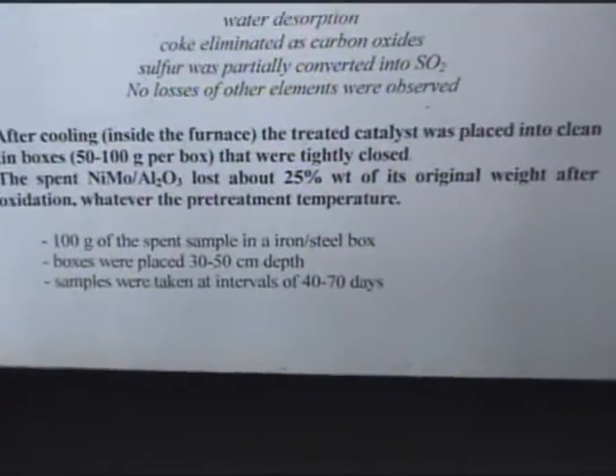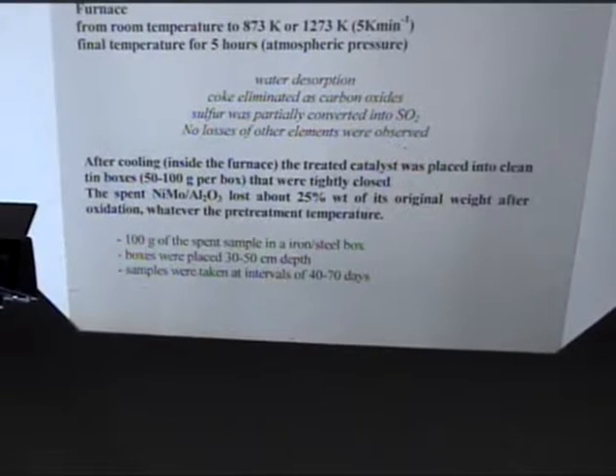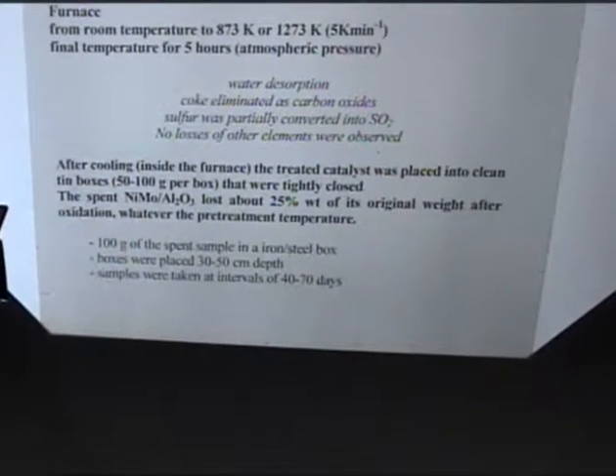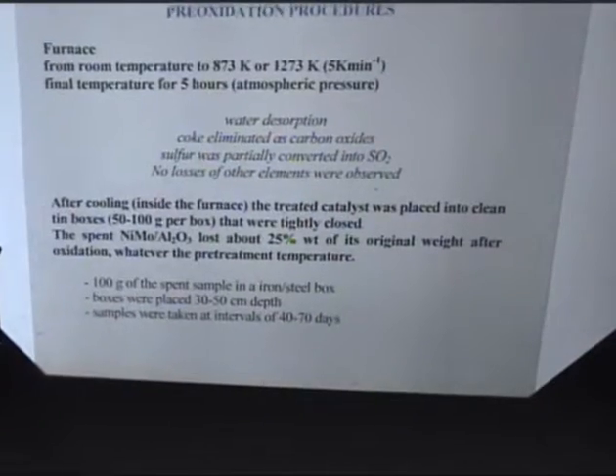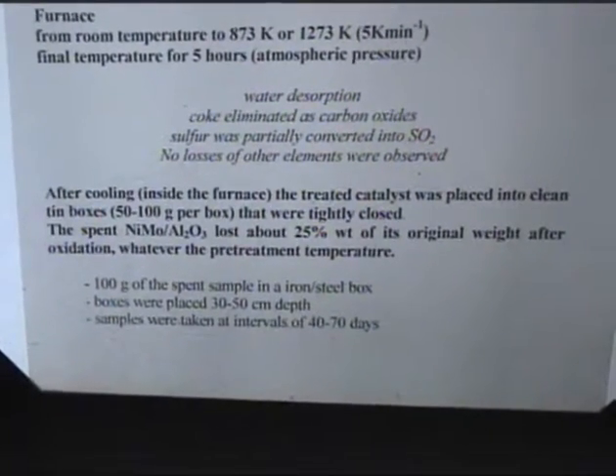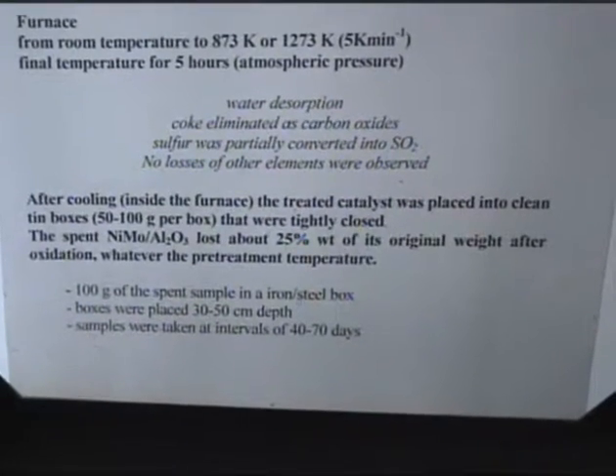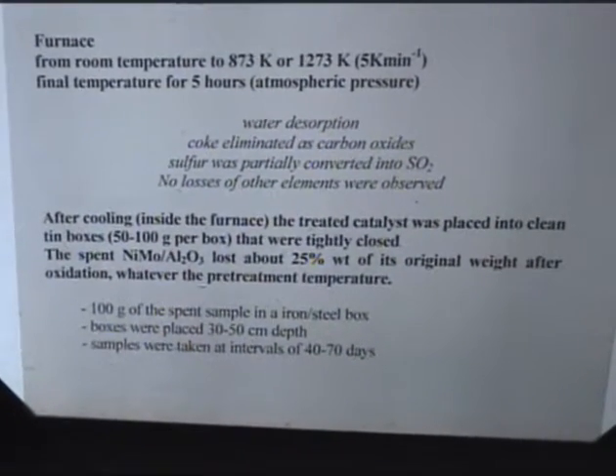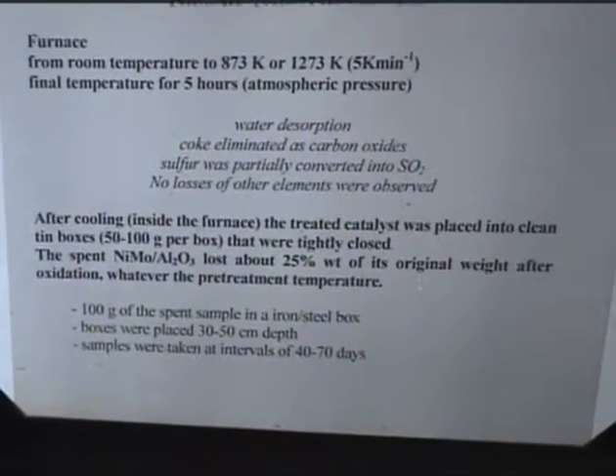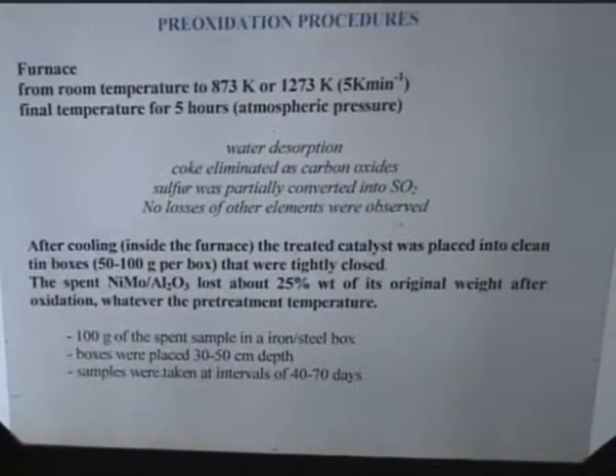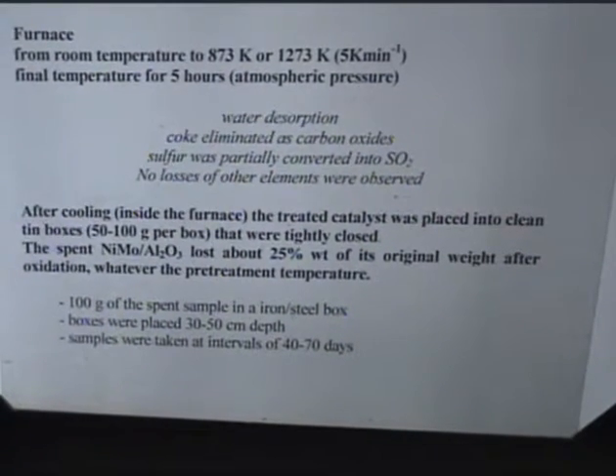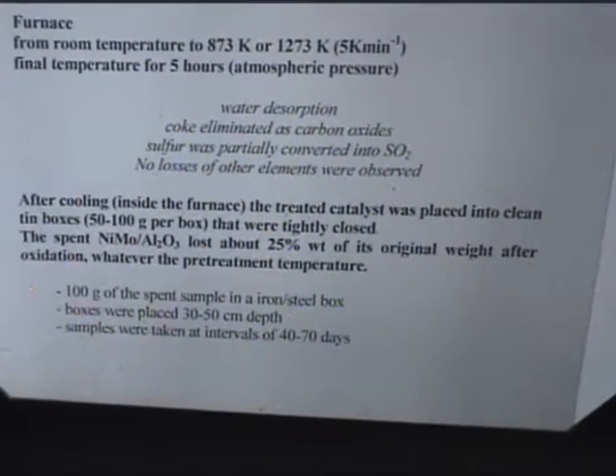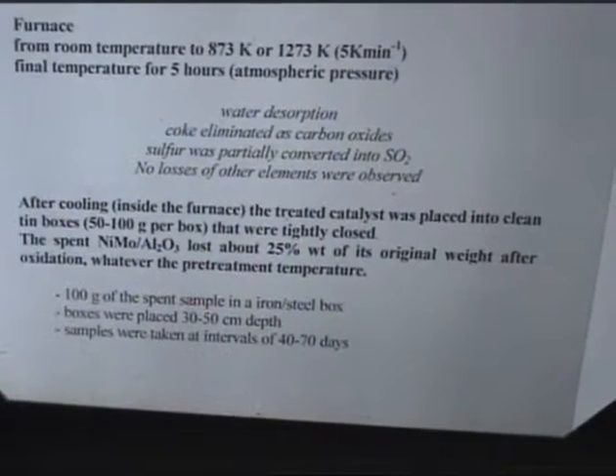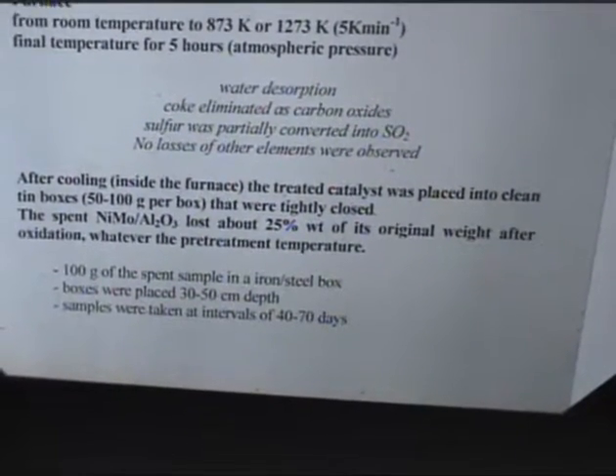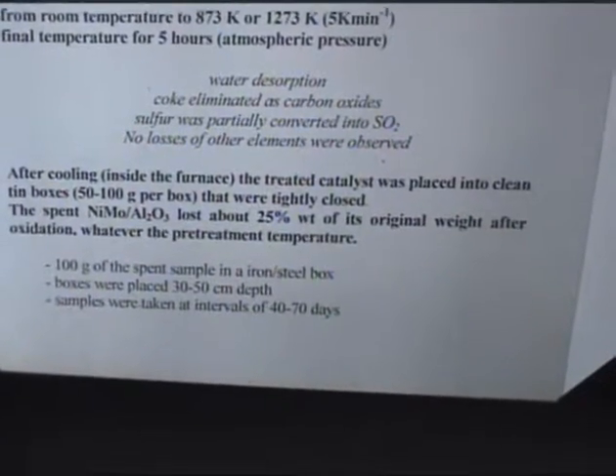After cooling inside the furnace, the treated catalyst was placed into clean tin boxes. These boxes are exactly the same as those used for food, milk, chocolate, coffee, and so on. Ordinary tin boxes that were tightly closed prior to burial. The spent catalyst used here lost more or less one quarter of its original weight after oxidation due to all these phenomena. The tin boxes were buried at a depth of 30 or 50 centimeters, and samples were taken at intervals between 40 and 70 days.